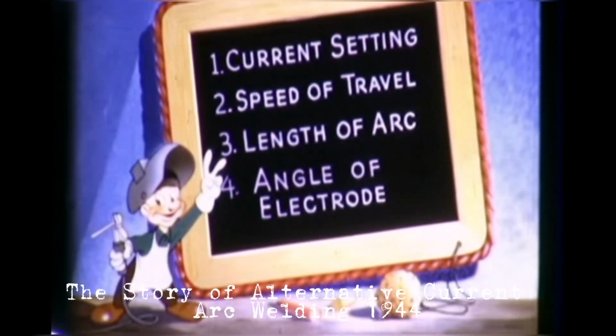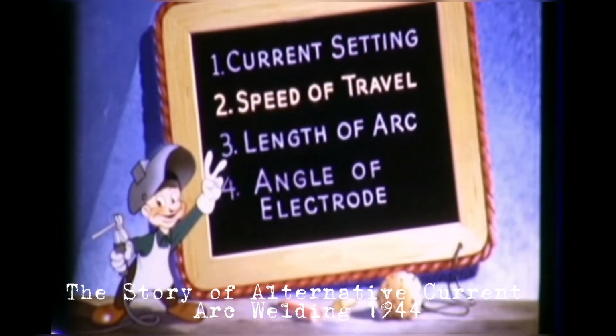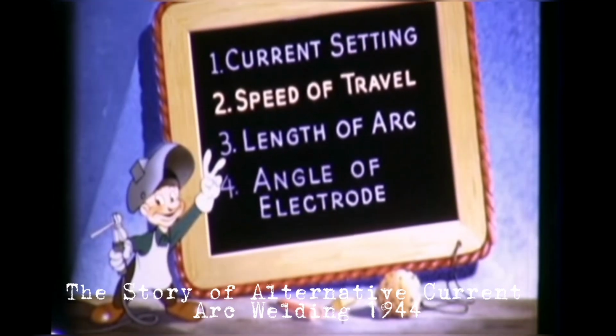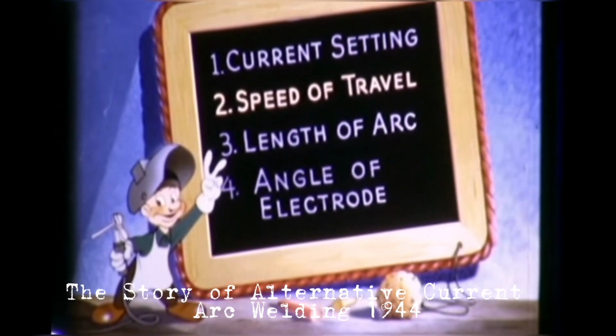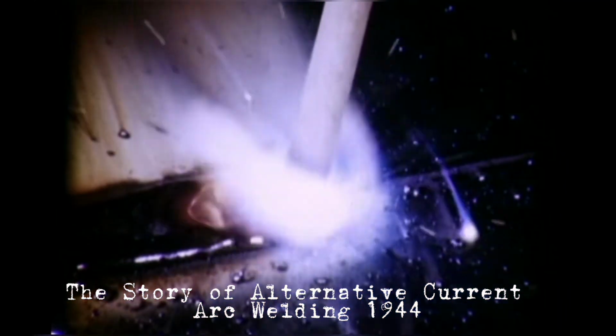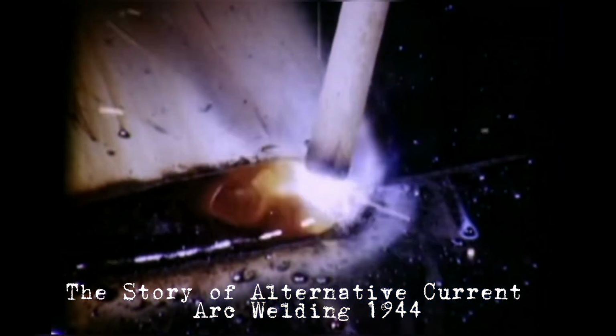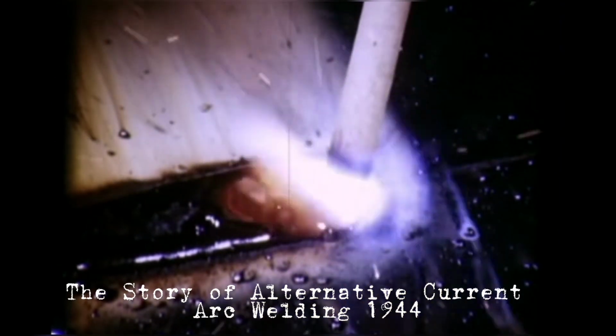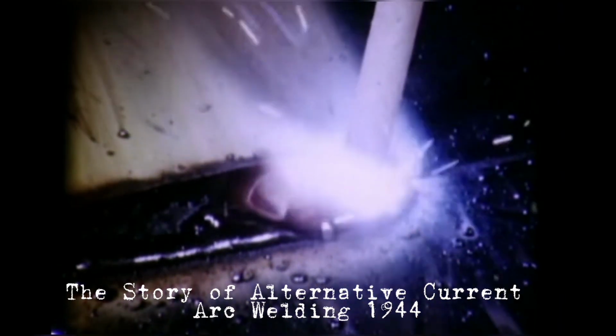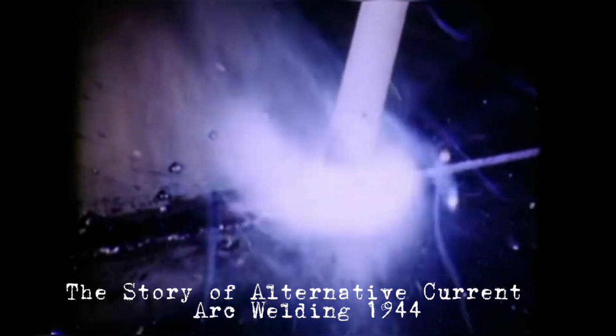The second factor, travel speed, must be suited to the thickness of the work and to the current setting and size and type of electrode. If travel is too slow, the molten metal piles up and there is danger of burning through the work. With too fast a travel, fusion is poor and the weld is narrow and irregular.